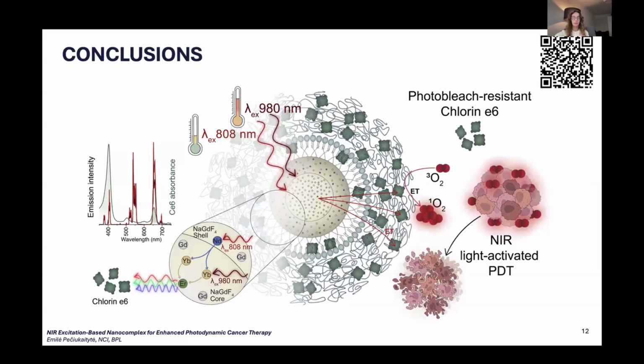we successfully developed an upconverting nanoparticle chlorin e6 nanocomplex, which is stabilized with phospholipids and resistant to photobleaching. The system shows efficient energy transfer, produces singlet oxygen under near-infrared light irradiation, and accumulates in cancer cells while maintaining excellent biocompatibility. Most importantly, it induces significant photodynamic effects, especially under 808 nanometer laser excitation. Overall, this work highlights the potential of this nanocomplex for deep tissue and near-infrared activated photodynamic therapy.